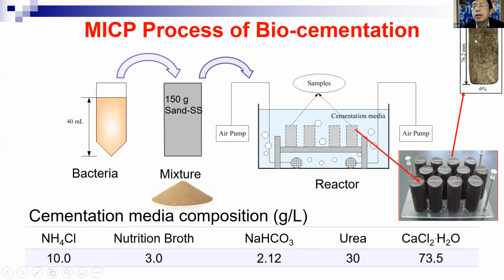We cut this geotextile with scissors and throw it away. So the sample looks like a cylinder shape. That depends on what testing you want to do. If you want to do unconfined compression testing, you can keep this cylinder shape. But if you want to do direct shear testing, you have to use a different size. So it can be decided what size to use. Since we are using this method, we call it the immersive method, basically immersing into the cementitious media. The literature also shows someone using the injection method, where they keep pumping the bacteria in and pumping out. So this is another way to do this MICP.